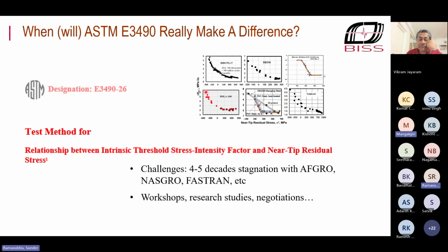curve. But you can use this curve to model how the crack will grow under a given load spectrum. That's what you can model, because there you're basically using applied mechanics equations. There's no fudge element over there. And for each load cycle, you are computing the sigma star, that is the near-tip residual stress, and picking off the ΔK threshold associated with that and plugging it into your growth rate equation. That's what you do for each cycle.